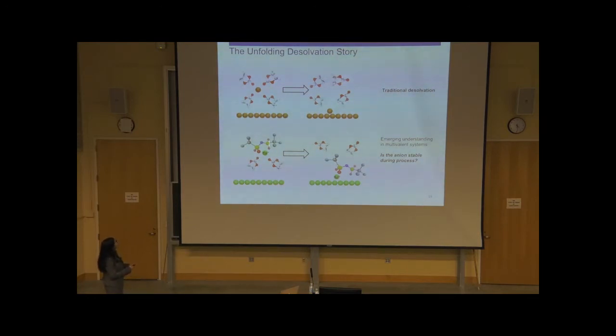So these results improved our understanding, and we found that the desolvation story in the case of magnesium electrolytes is not the same as for lithium electrolytes. Because lithium is well solvated by the solvent molecules, if you want to deliver it to the surface, all you have to do is strip away these solvent molecules. In the case of magnesium, because it has such a strong tendency to bind with the anion, even if you strip away the solvent molecules, the anion will act as a delivery vehicle to deliver this magnesium ion to the surface.